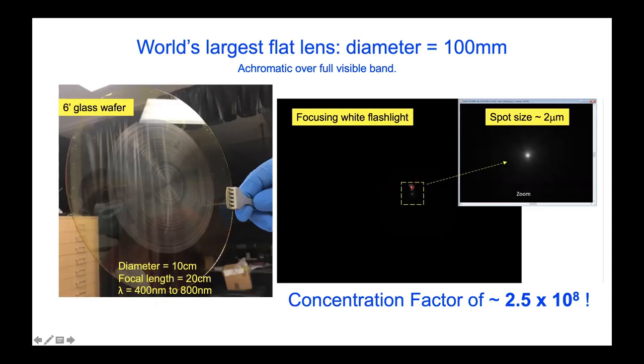And this is a very simple experiment. We took a white flashlight, expanded it, and focused it down to a spot size of something like 2 microns. And if you really think about this, this is an incredible concentration factor for something like, sorry, 250 million X. So it's a pretty insane amount of concentration. In fact, of course, if you put this under sunlight or something like that, it's quite a dangerous experiment to do to some extent.